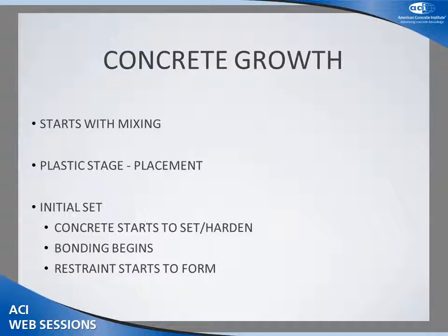Subsequently, as the concrete goes into its shrinkage phase, there will be more shrinkage cracking. If we provide restraint for the expansion, defined as restrained expansion, the concrete specimen will maintain its as-placed volume and no shrinkage cracks will develop. The restraint transforms the concrete expansion into a compressive strength in the concrete. And the key to eliminating shrinkage cracking is developing the restrained expansion.